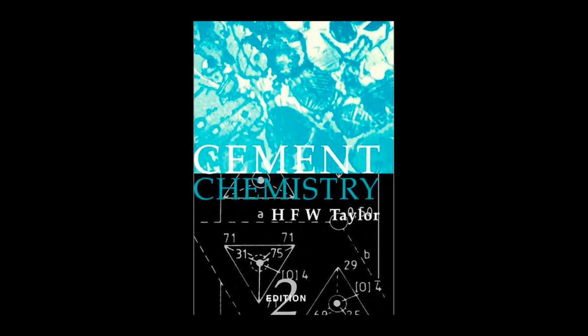Exactly. This is one of the most persistent real-world engineering problems in the industry. These recycled species form low-temperature melts, complex alkali, sulfate, and chloride systems that can start melting dramatically below 700 degrees Celsius. So you've got liquid way too early in the process. Way too early. Think of it. Material that is still relatively cool, well before clinkering temperature, is turning into a sticky, low-viscosity liquid. And that sticky liquid coats dust particles, causing them to adhere aggressively to cooler surfaces and narrow passages. This leads to the formation of these hard, obstructive kiln rings and deposits in the preheaters.